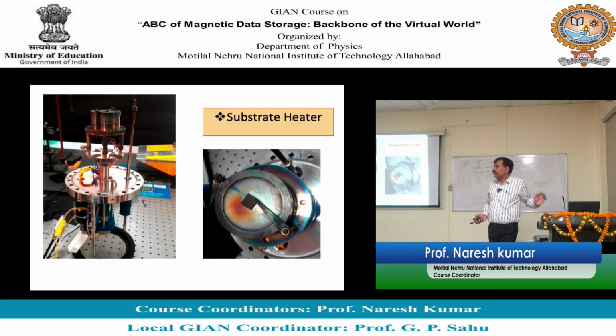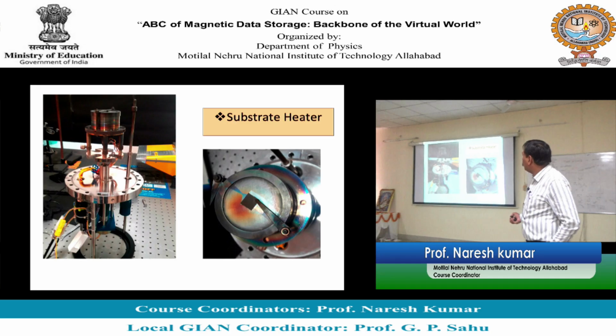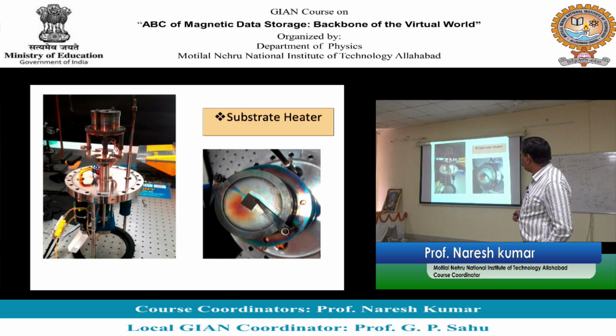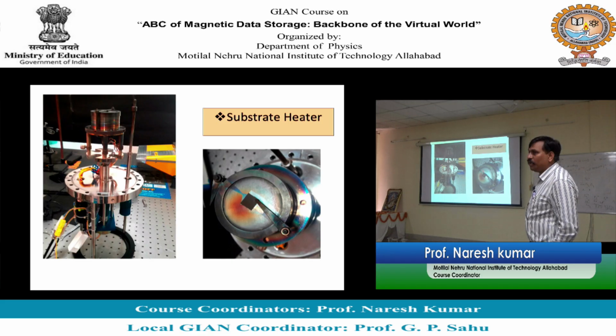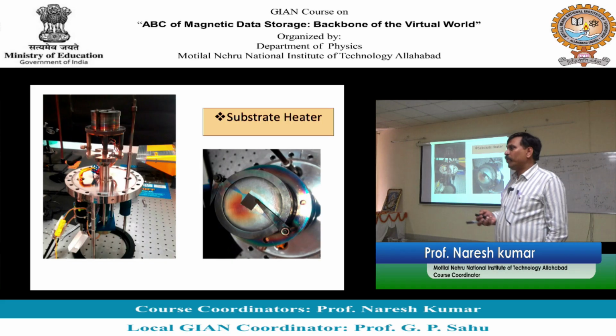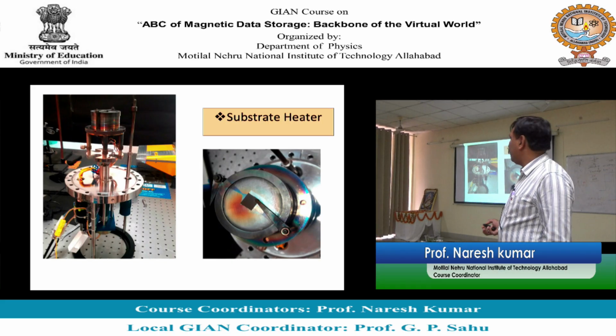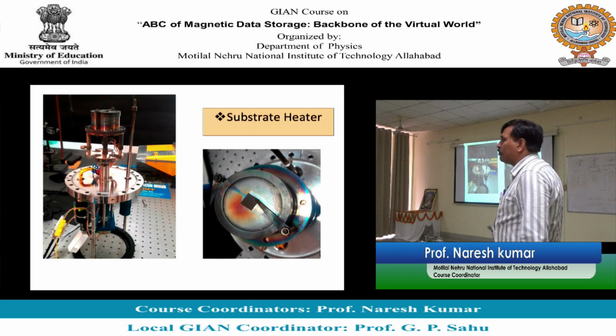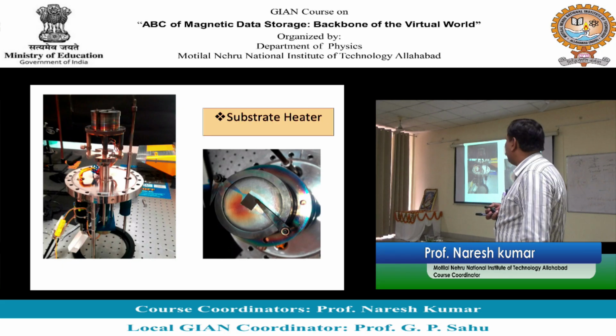And this is the substrate heater. There is an arrangement for heating this and measuring the temperature. This is the top surface of the heater where we mount our substrate. For mounting the substrate, we use either a clamp or some conducting paste, so that there is no temperature gradient from the surface of the heater to the surface of the substrate, right?